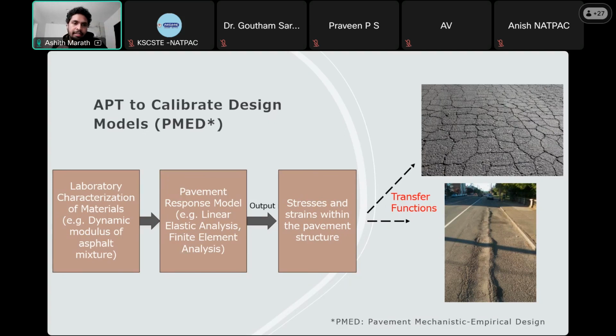So once you characterize the materials, you use some pavement response model, which could be linear elastic analysis. So in our case in India, we use IITPAVE, which runs on a linear elastic analysis program. And it could be a finite element analysis program as well. And the output from the pavement response model will be the stresses and strains within the pavement structure. More specifically, as pavement engineers, we focus on the critical locations, that is the strains at the bottom of the asphalt layer, and also the vertical strain at the surface of the subgrade layer.